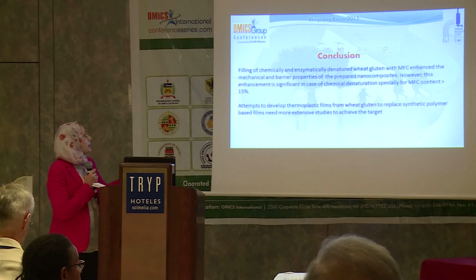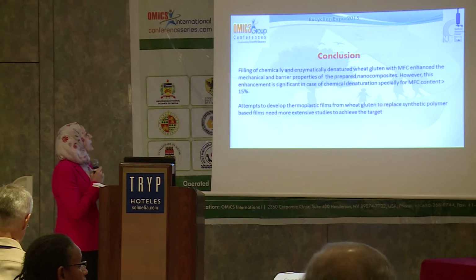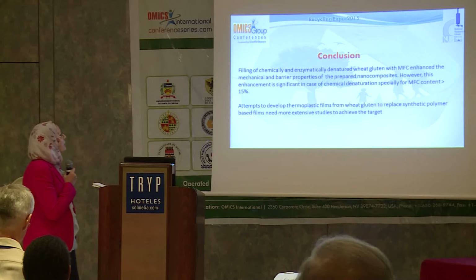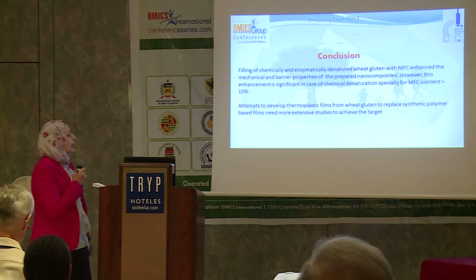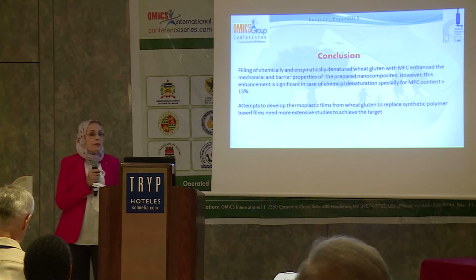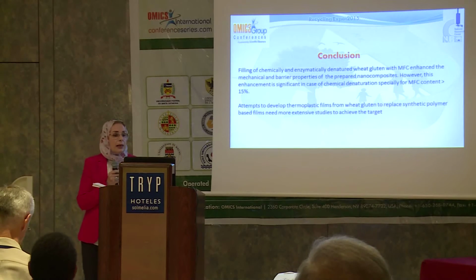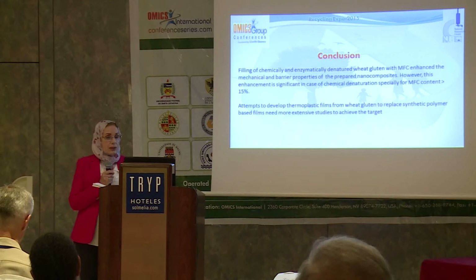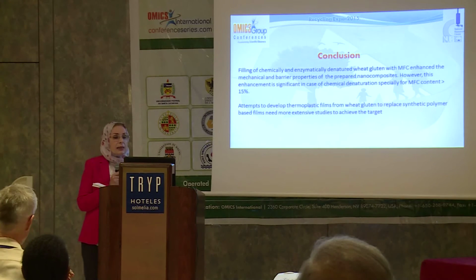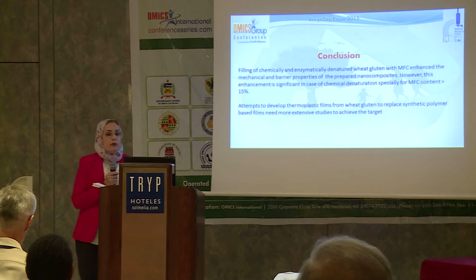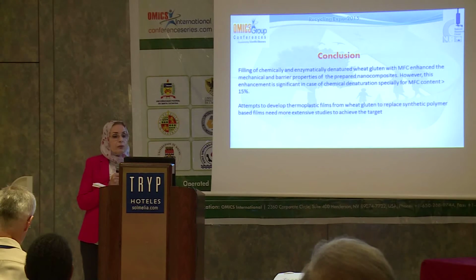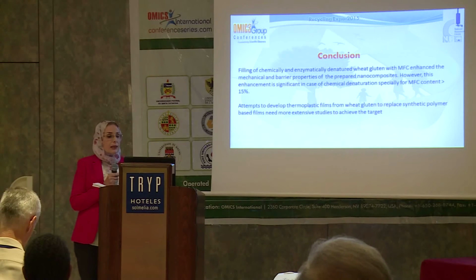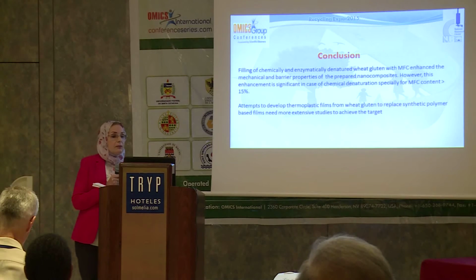also in the prepared films. We can conclude that filling of chemically and enzymatically denatured wheat gluten with microfibrillated cellulose enhanced the mechanical and barrier properties of the prepared nanocomposites. However, this enhancement is significant in the case of chemical denaturation, especially for microfibrillated cellulose content more than 15%. Also, attempts to develop thermoplastic films from wheat gluten to replace synthetic polymer-based films need more extensive studies to achieve the target.